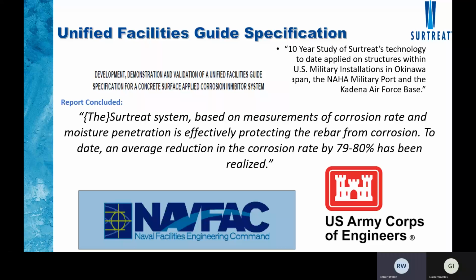Most of these structures were built back in the 1950s during the Korean War. And with time, carbon dioxide in the air and salts from the environment had penetrated the concrete and caused corrosion. We treated the concrete and measured corrosion rates, strength, and porosity before application. And then over time, the Corps of Engineers and NAVFAC sponsored other independent consulting companies to go back and continue to measure these properties. And what we found is that over a 10-year period, the corrosion rates continued to be reduced by 80% from what it was when those corrosion rates were originally measured prior to the first application.